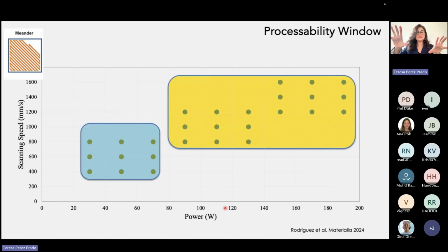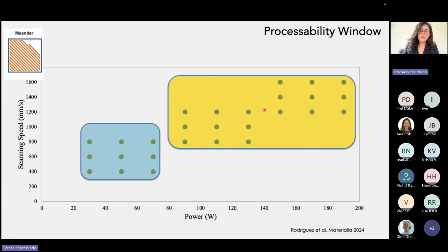And I have divided this in two regions. This orange region was an area corresponding to relatively high powers where we couldn't even print cubes. So within this very large processing window, there was delamination, as you can see there was excessive melting. It was impossible to even keep the shape of the cube. But within the low power region, yes, we could at least print cubes. And what I'm going to show you there is, well, we want to, of course, keep the shape, but we want to have a fully dense and also fully amorphous material. So how are we doing there?